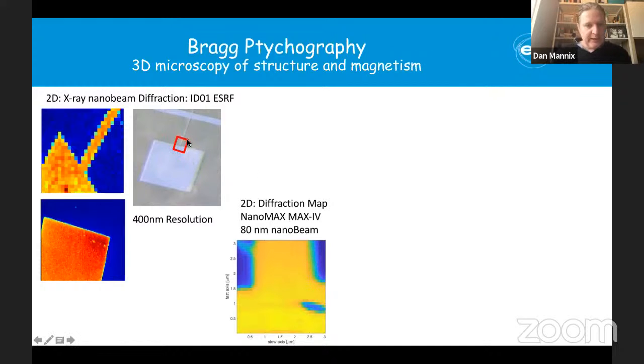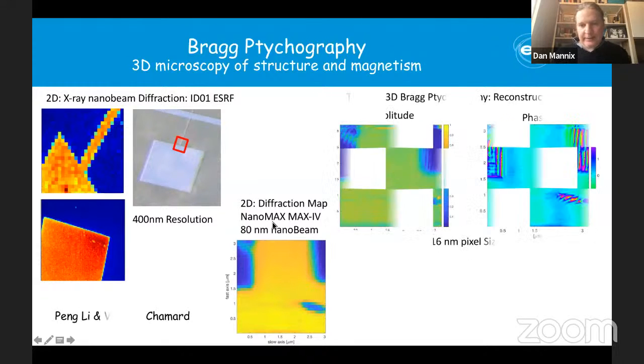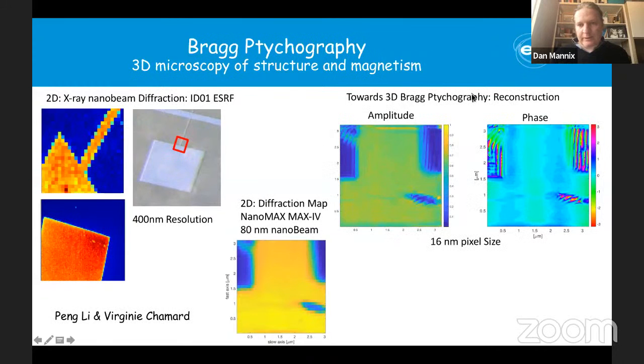We have actually started to do these experiments at the NanoMAX beamline, looking at the structure of these materials. Here we zoom into this structural area, and this is the total diffraction map. I'm away from circular polarization for the moment; I'm just looking at the structural information that's given off from this material. And here we show the Bragg ptychography reconstructions from that area. This has been done in collaboration with Peng Li and Virginie Chamard, who are experts in ptychography, and they're working with us on this project of trying to develop magnetic ptychography.